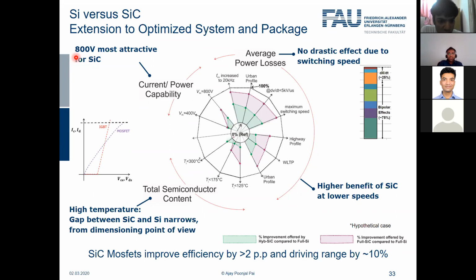So to summarize here, we saw that silicon carbide MOSFETs improve efficiency performance by more than 2 percentage points, meaning that you go from something like 96.5 to 98.5 efficiency. And the impact on the driving range was in the range of 5 to 10%, again depending on the mission profile.